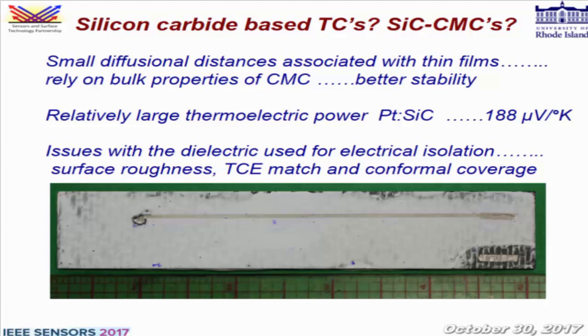As you guys know, thermocouples are just made of two conductors which are connected at a point. And so we thought that we could potentially use this silicon carbide CMC material as part of the thermocouple. The little picture below shows one of the thermocouples that we actually made. If we could incorporate this material as part of the thermocouple, we could bypass all of these issues that affect thin film thermocouples.